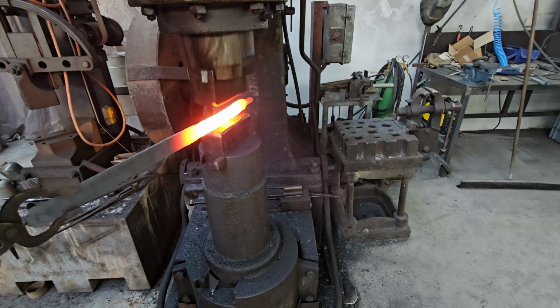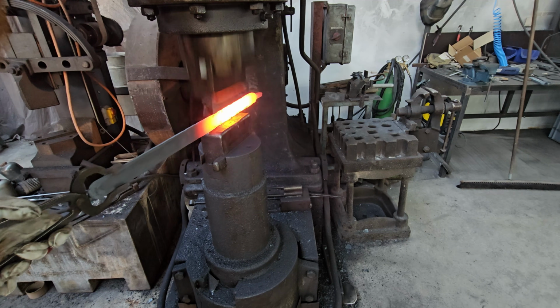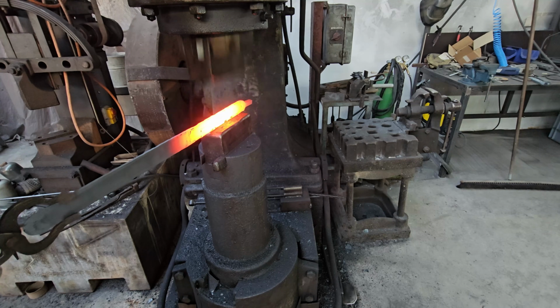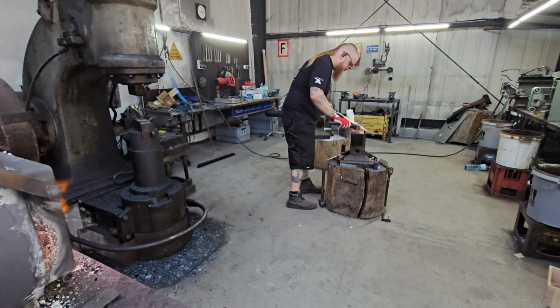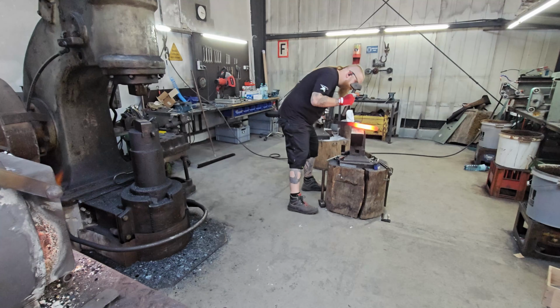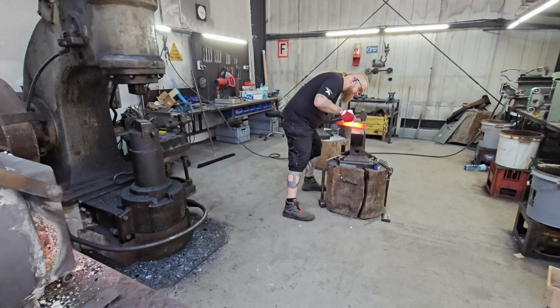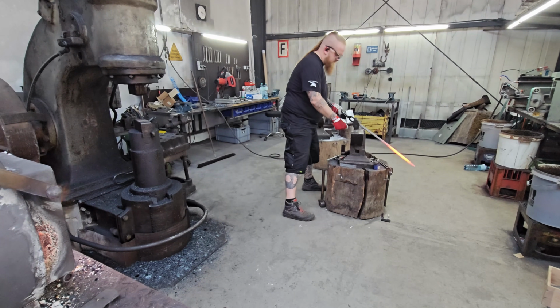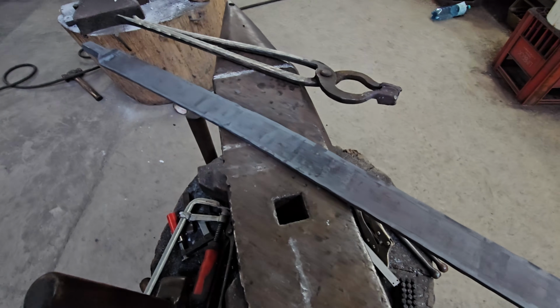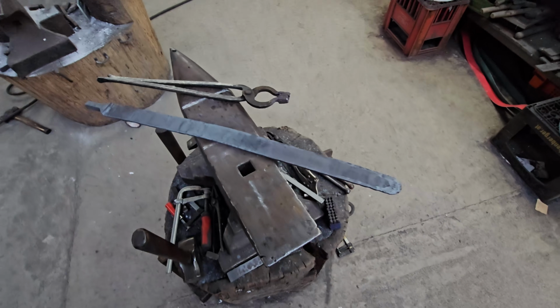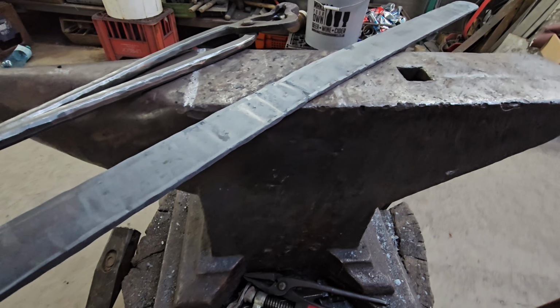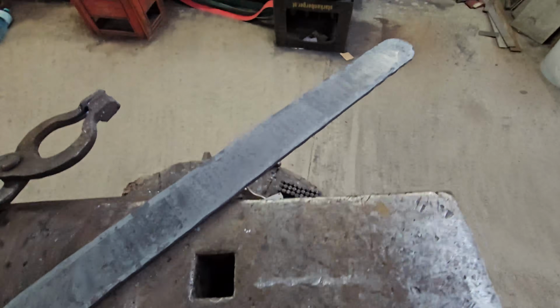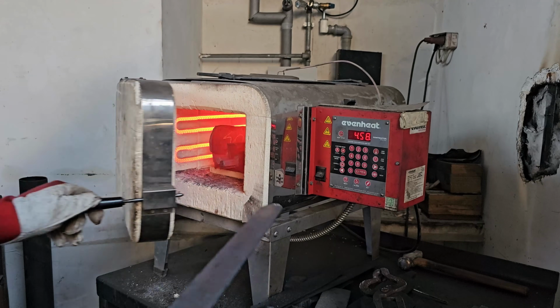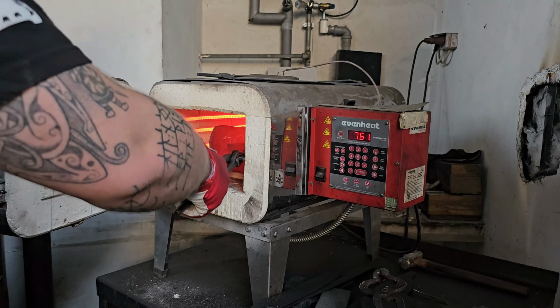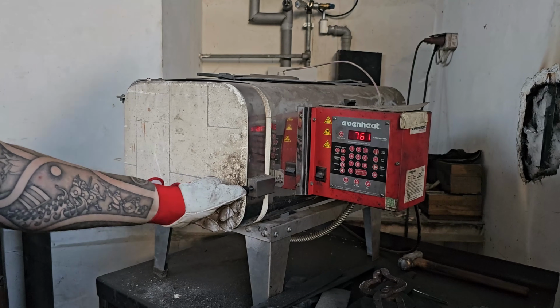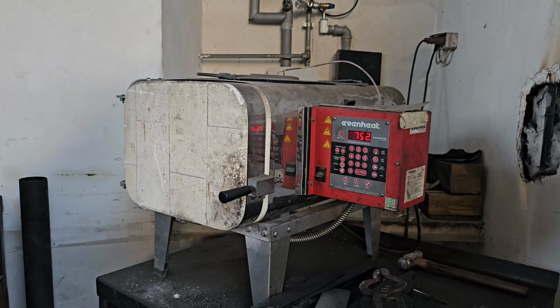Forging the piece out to our width and the thickness that I want. And now on the edge, just give it a few taps just to have this little curvature that is needed for a Wakizashi. In the end, since it's Sanmai, I don't really forge too much into a profile with this kind of piece, because I want the Damascus to be as big as possible on the inside. Putting it into the heat treating oven at 780 degrees Celsius, keep it there for 2 hours and then let it cool down with the oven overnight.